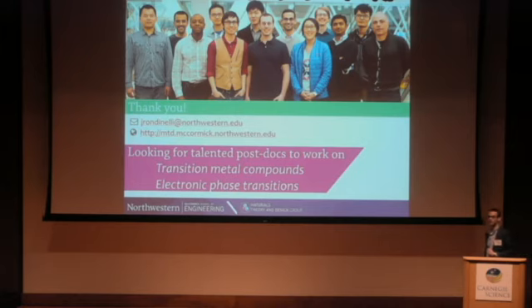You mean in the calculation? Have we looked at their energies? For this family, we haven't. Those we've looked at in the manganites. There is competition between other polymorphs between 2.5 and 3. Experimentally, the problem is if you make a brownmillerite, you find the full whack. Yes. You find lots and lots of other phases in between, which are sort of incomplete brownmillerite, but they are stable phases. Yeah, so performing a traditional solid-state chemistry reaction, you do get this polymorphic competition.